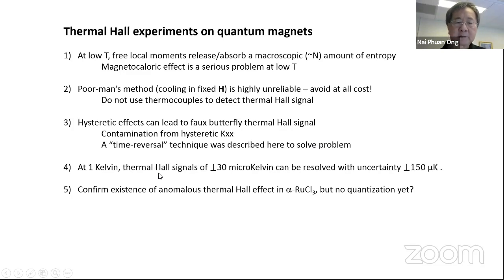So currently the thermal Hall resolution is very good. We can impose a 100 millikelvin gradient across a small crystal and detect 30 microkelvin transverse difference. So that's sobering, right? However, because of these uncertainties, extrinsic effects, we can only vouch for maybe 150 microkelvin uncertainty. But anyway, this can be improved as time goes by, right? So there's something to work on.